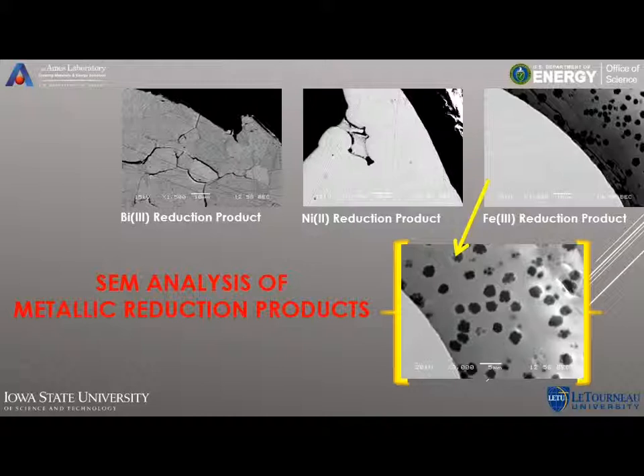And so with a little more thought, it seems likely that these dark areas, dark patches, are actually bubbles in the material. If you consider what's going on, it's a reduction process, and so the iron oxide is being reduced by carbon, and the oxygen is binding to the carbon and creating carbon dioxide. And so you'd have this outgassing of carbon dioxide forming these bubbles in the material.